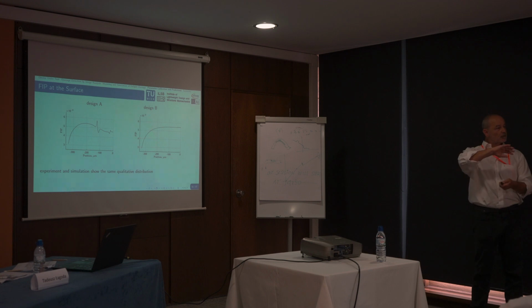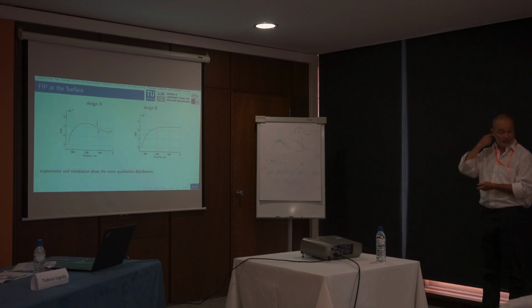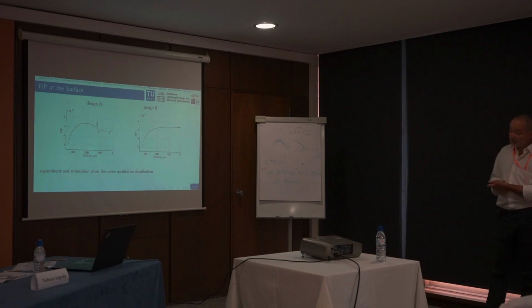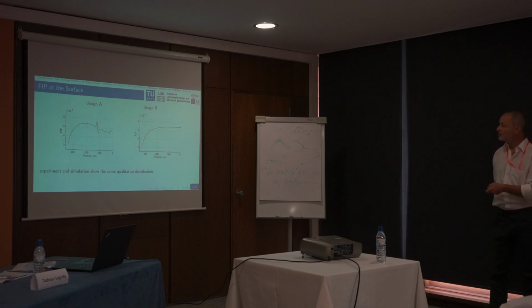It's qualitatively similar to what we see on the surface cracks, on the crack density, and in addition, in the indicator, we see here also this effect, which comes from this small step on the copper surface. So we have actually here 2 effects. This is a geometrical one, kind of a notch, and this is coming mainly from the temperature of the device.